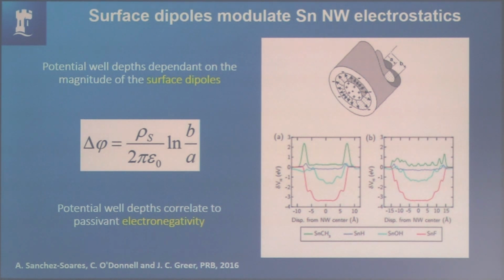But anyway, alpha tin has the same structure as silicon. It's a diamond lattice, and it's a semi-metal, zero band gap, but it has somewhat conventional chemistry in the fact that the bonding is very directional. In bismuth, less so, very much more complicated. And what you're looking at here is basically if I put fluorine on the surface and I pull a lot of charge out, that means I have a lot of positive charge stuck in the wire. It looks like a coax cable. And basically, I get this difference in potential. This difference in potential is what's giving me the difference in the band gap.